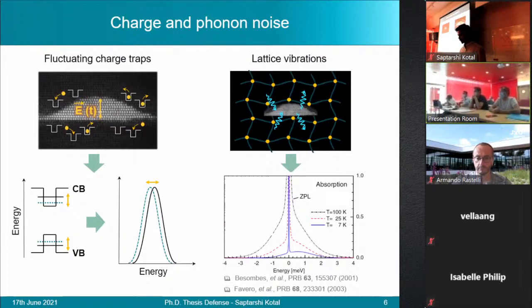Two main effects of such a coupling can be observed. First, we notice the appearance of two phonon sidebands on either side of a spectrally thin Lorentzian line shape, which is called the zero phonon line. Particularly on the left side, the sideband corresponds to the emission of a photon associated with the absorption of a phonon. And on the right, we have the emission of a photon accompanied by the emission of a phonon.